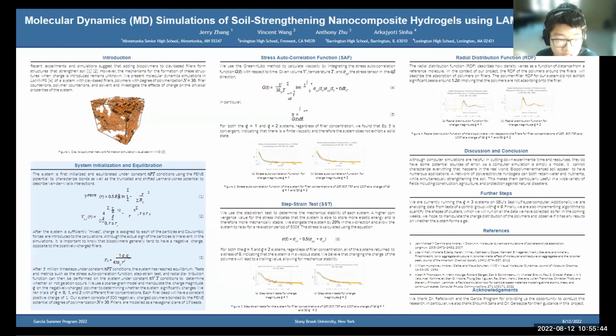If the integral diverges, then it indicates infinite viscosity, which implies that gelation has occurred. However, according to our results for both biopolymer charge magnitudes of Q equals 1 and Q equals 2, the stress autocorrelation function converges to 0, which indicates that our system exhibits liquid-like behavior.